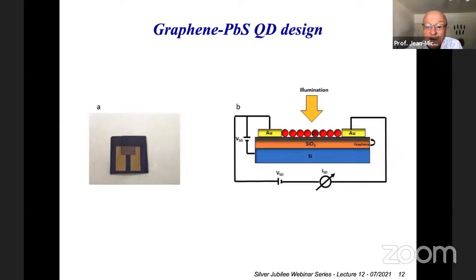So the photodetectors we are using in that situation are very simple. We have a layer of graphene, which is a CVD deposited graphene on top of silicon oxide, purchased from a company. There are two companies selling this, one in Spain and one in USA. Probably other companies are selling these wafers. So the wafers are 2-inch wafers. They are kind of big already. And we cut little squares, like 1 square centimeter, like these ones. Actually, that's CVD graphene monolayer deposited on the silicon oxide on top of silicon.